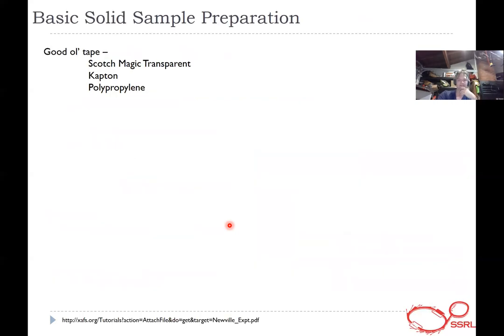And I'll give you a quick overview of a basic solid sample preparation. A lot of times, good old tape is just the way to go. You can use Scotch Magic transparent tape, Kapton tape, and polypropylene. These are all generally available at the synchrotron if you can't get them. But you need to beware of impurities in your tape. If you're looking at the sulfur edge, you need low sulfur tape. Scotch tape, I can't remember, but it has some metals in it. So if you're unsure, you can definitely put a blank piece of tape in the beamline and see if you get any signal from it, especially in a fluorescence experiment.